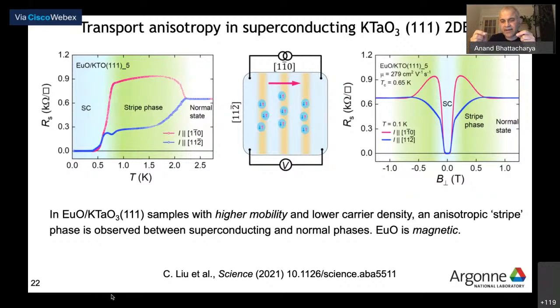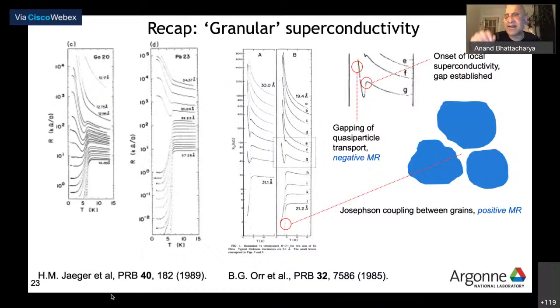Because there is a gap in the grains. Oh, here's the picture. There's a gap in the grains, and the quasi-particle current can't overcome that gap. And that's why the resistance rises. This is the famous work done in Alan Goldman's lab back in the late 80s and early 90s, and even before that, and other groups as well.